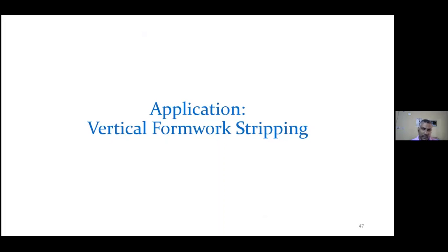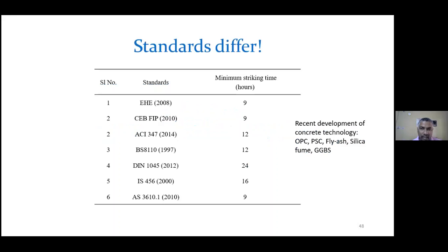So we have applied this procedure to vertical formwork stripping. When you have to remove the formwork, I told you about the Skyline Plaza accident, where people removed the formwork prematurely. So we have checked the codes to see what the different times are. There are different codes: CEB-FIP, American Concrete Standard, British Standard, German DIN, Indian Standard, Australian Standard. They say you can remove the vertical formwork after 9 hours of casting, and some other codes say 24 hours of casting. So it varies from 9 hours to 24 hours.